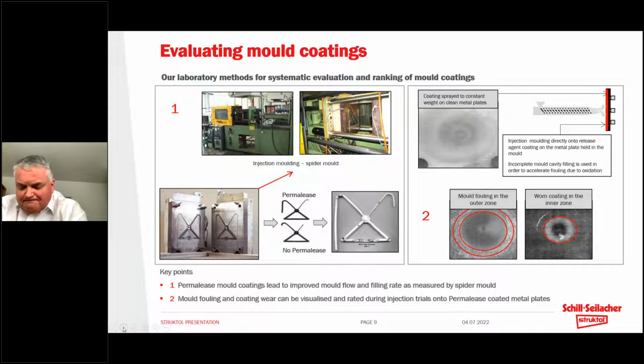surface coating. What we can do is carry out a number of injection cycles on a cleaned mold, and this of course will allow us to not only rate the degree of mold filling, but also subsequently measure the degree to which the mold has become fouled. One of the ways that we can do this is after making a number of injections, let's say 20 injections with our compound to create mold fouling, we can then switch to a mold cleaning compound.